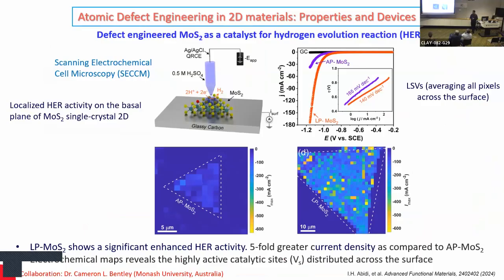Then we all know that these defects in 2D materials are useful in catalysis applications as well. So in collaboration with Dr. Cameron in the chemistry department at Monash, I contacted him because he has this very nice SECCM technique, which can map the defects on 2D materials over an area. So I gave him the low pressure CVD grown MoS2, which has sulfur defects in it, to map it.